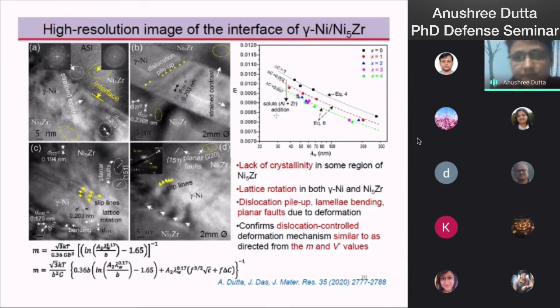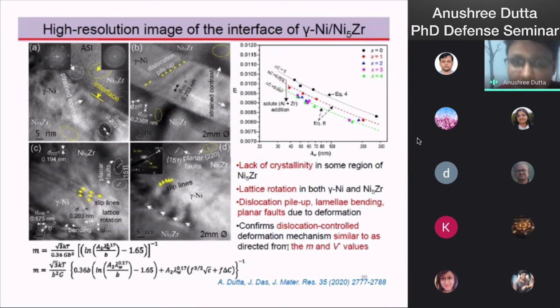Then both the values from the strain rate sensitivity and activation volume confirm that the dislocation mediated deformation mechanism is controlling for these NECs, whereas the HRTEM microstructure also confirms that the dislocation mediated deformation mechanism is controlling for the entire lamellar thickness region from ultrafine 39 to 275 nm.